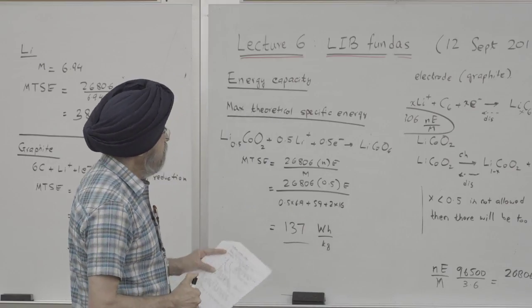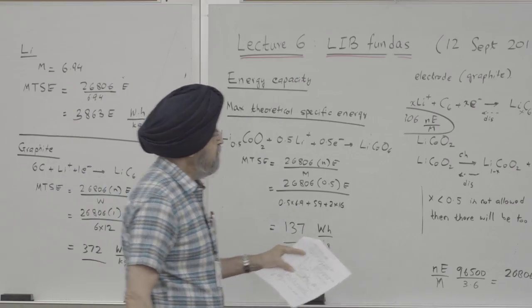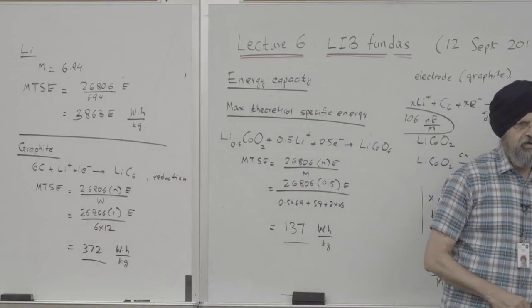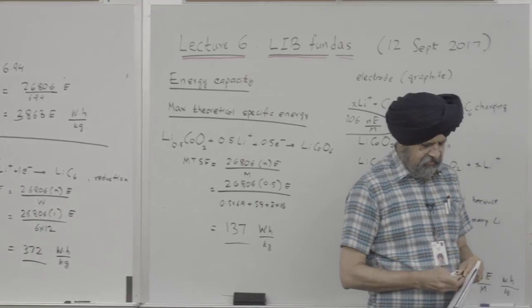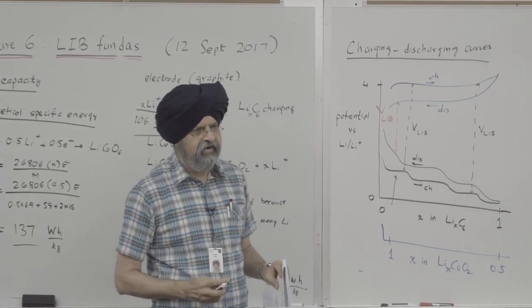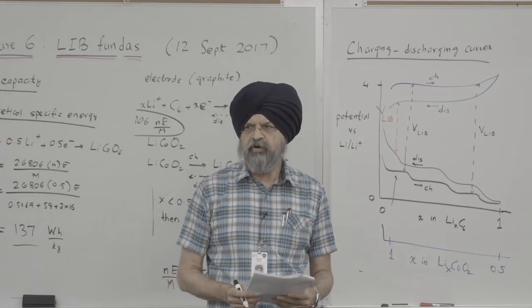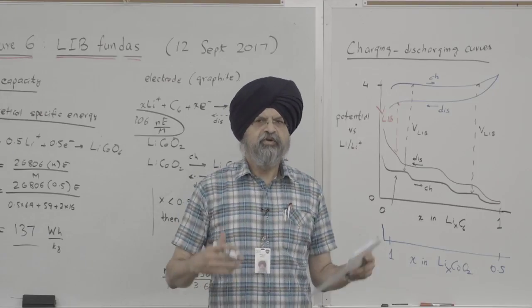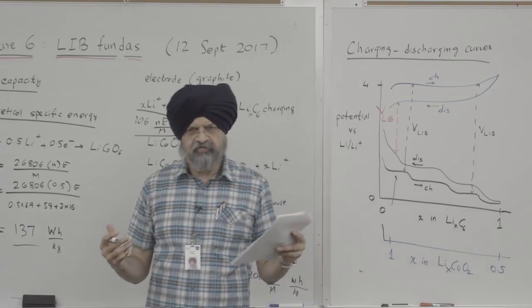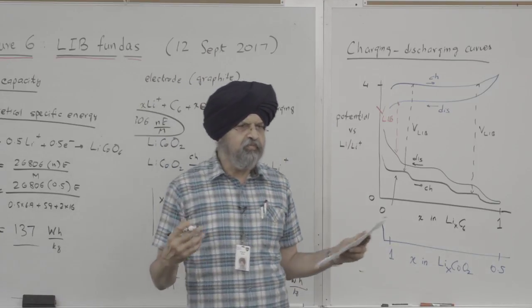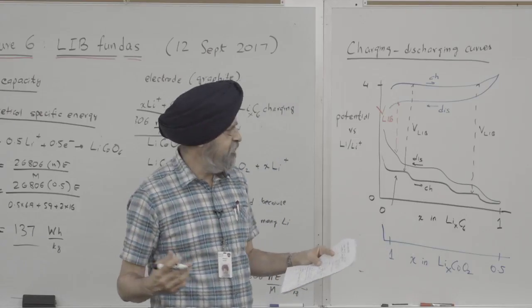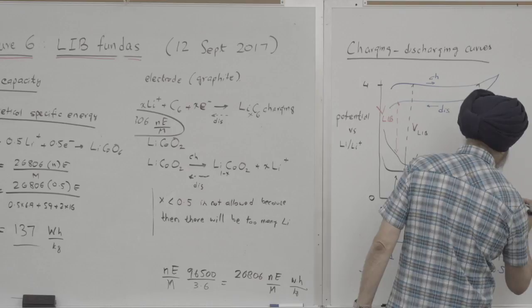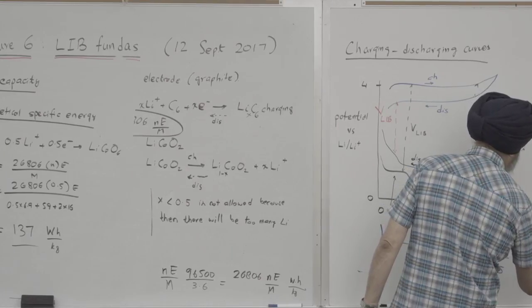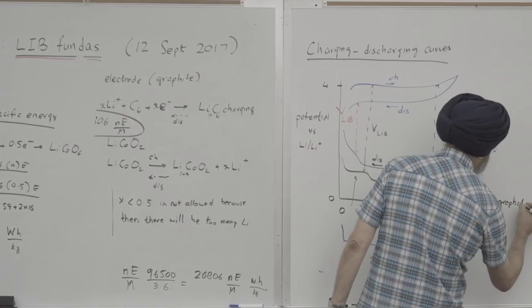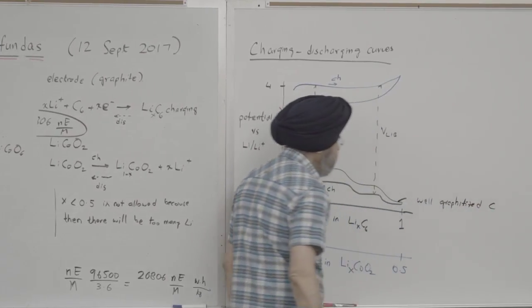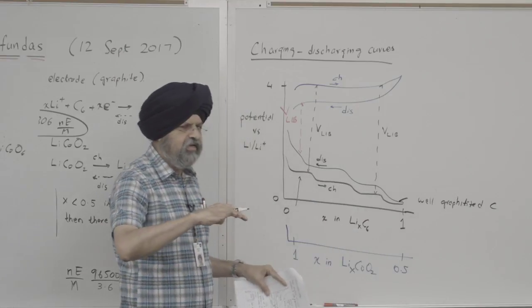Okay, so back to the charging-discharging curve. So this curve I've drawn is for well-graphitized graphite. So how do you make graphite? You take carbon, it could be in the amorphous form, and then you heat it up to a very high temperature, like 2500 degrees centigrade. So the amorphous carbon will become graphitic. So here, this curve I've shown is for a well graphitized, let's say, carbon.